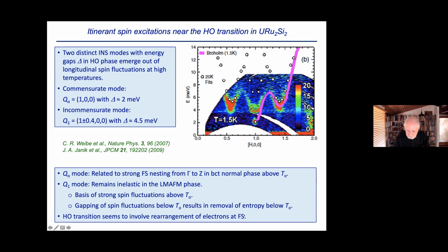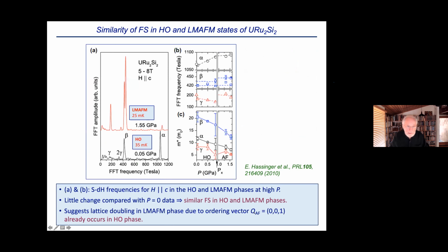ARPES work done with Andrés Santander-Syro just came out in PNAS, shows that the Fermi surface topology actually does not change when you go into the large moment antiferromagnetic phase, but there are portions of it that do change a small amount. Some features do not change as you go into the antiferromagnetic phase. So it seems to be very, very subtle. And this is the SdH measurements. So you see the amplitudes versus frequency. This is in the hidden order, large moment antiferromagnetic phase.